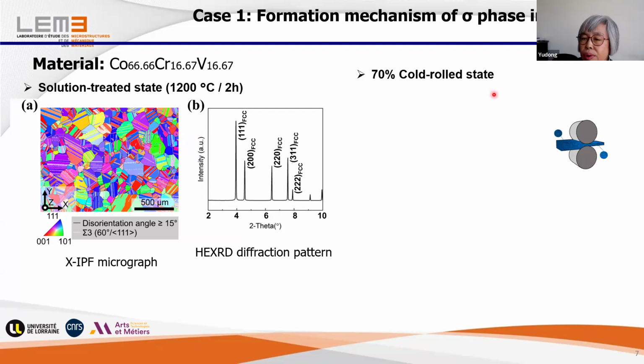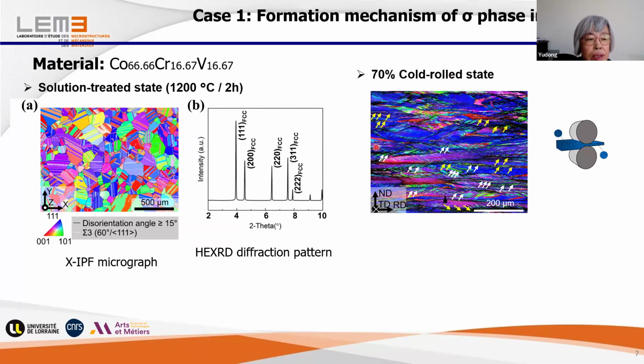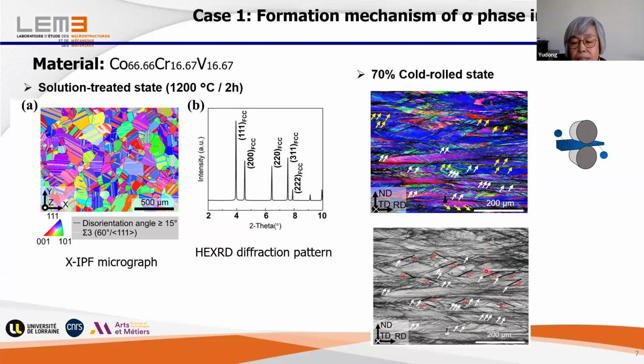After that, we made a cold rolling with 70% reduction. The microstructure looks like this. The equiaxed grains become elongated along the rolling direction. And the important thing is we see a lot of slip bands with band contrast in the EBSD map, outlined with clearer black lines. We counted the angle of these shear slip bands with regard to the rolling direction, and we can see they are in this range. I will show you something later with this characteristic.